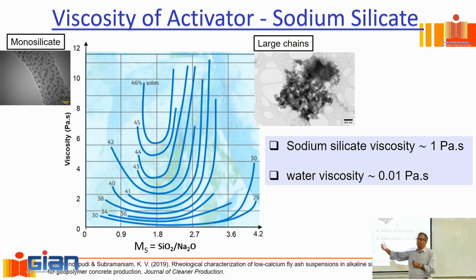It has to hold before the kinetic reaction kicks in, and then the material starts to harden because of the reaction. Then the reaction will take over, right? So whether it's a matter of a few hours, or a day, this structuration has to hold for that duration. How quickly should the structuration happen? Matter of seconds. Why? Because you smash the structure when you pump it, right? You're subjecting it to high shear. What is the high shear doing? It's completely shearing off the material. Any floccules, any structure that's there is sheared off. Then you deposit it. It comes to rest. And then before the next layer comes around, this fellow has to rebuild its structure inside.